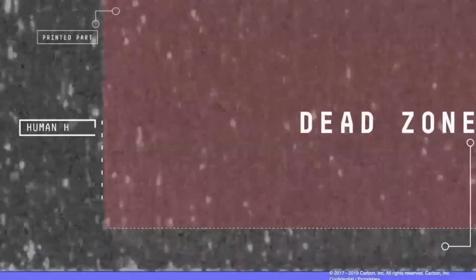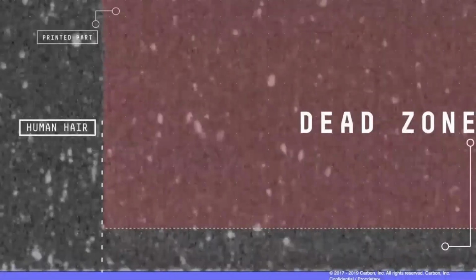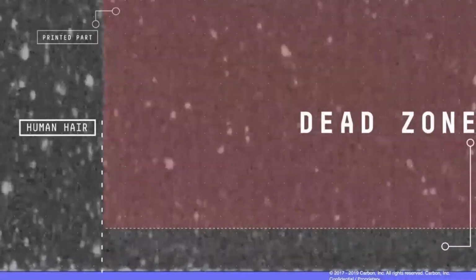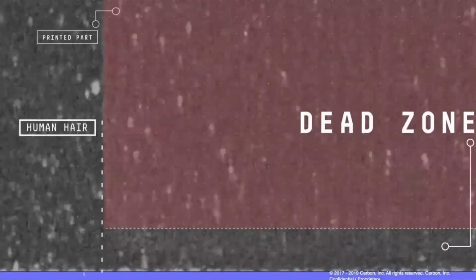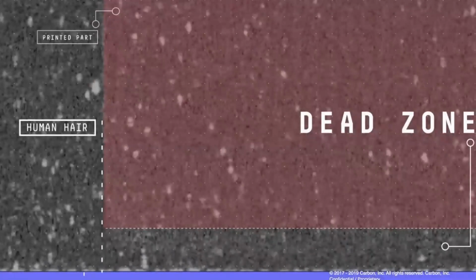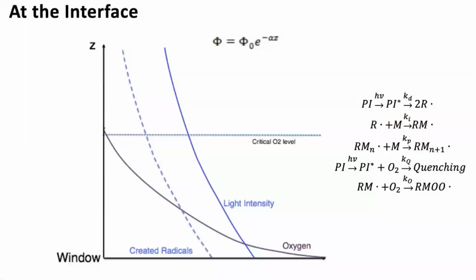It's a chemical renewal approach as opposed to a mechanical engineering approach to bring fresh resin into the build area. This allows you to go really fast. You avoid the layer by layer approach, and we can print 100 to 1,000 times faster than traditional approaches when you're operating in this continuous mode. And so we've worked out a lot of details of this.